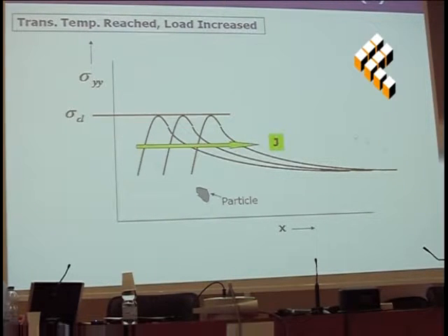the bad guy, and then I can predict the J integral at fracture for the transition temperature. This is supposed to be the transition temperature, and at the transition temperature I can have different J values depending on the location of the critical particle. Okay, this gives me the scatter. This is the model, and we'll see in a moment that it's kind of true.